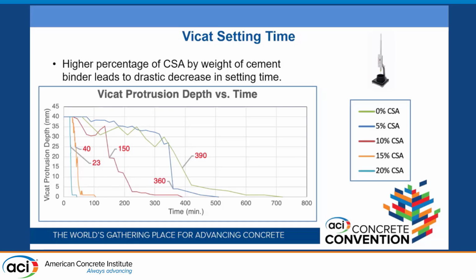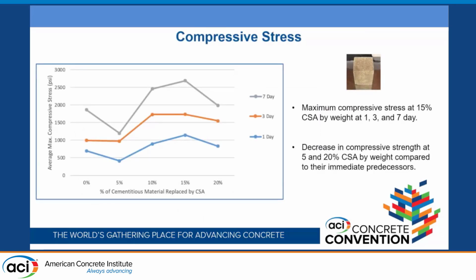Now, we started off by conducting our Vicat testing using ASTM standards, where we saw that there was a drastic decrease in the setting time of all 5 of our specimen as we increased the percentage of CSA replacement. So at its peak, the difference between the 0% CSA replacement, or no CSA, with 20% CSA replacement would be a 90% drop in setting time, which was really interesting to see. That's a difference between about 6.5 hours and 23 minutes.